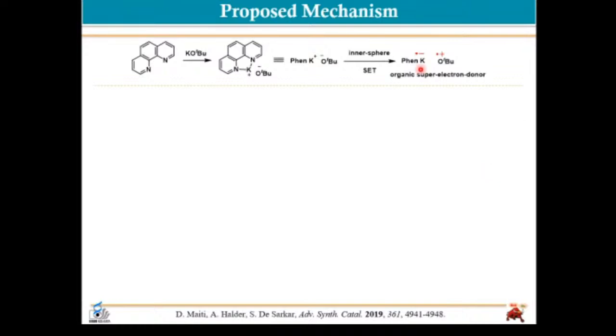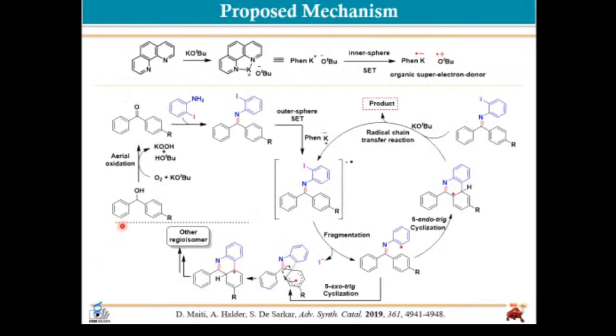So then what's happening? Here we go. We used an alcohol. In this case we did not use any inert atmosphere, no argon, no nitrogen, just air or oxygen. So in presence of base and oxygen, this alcohol is getting oxidized to ketone. We started with ketone and we got the product, that means this is the intermediate, as we said. So this is forming, and we have amine here in the mixture already. So once we form amine and ketone, it will of course condense and form this imine.